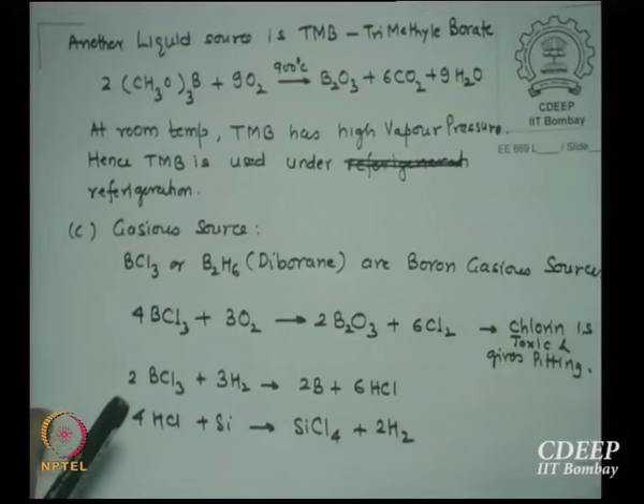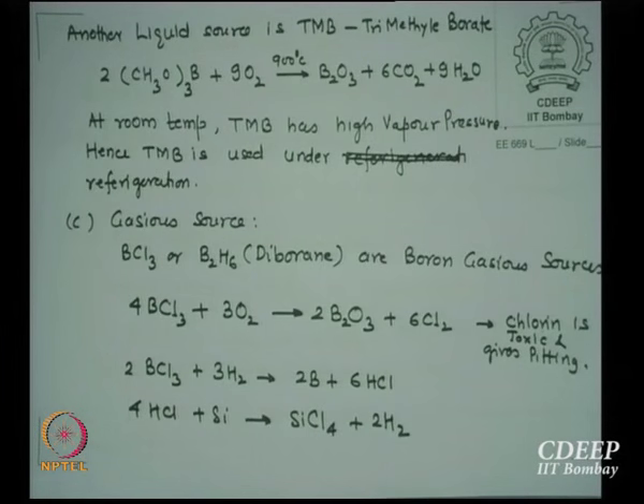If you still want a liquid source, then there is a source called trimethyl borate, which is used now. TMB is very popularly known. When TMB oxidizes, it creates B2O3, carbon dioxide and water. TMB has a problem that it has a very high vapor pressure, so it has to be refrigerated to keep the vapor pressure down, otherwise it blasts out. So it's always kept refrigerated, and even then you put it in a water bath and only then use it.